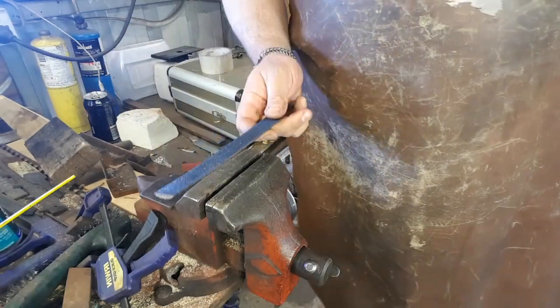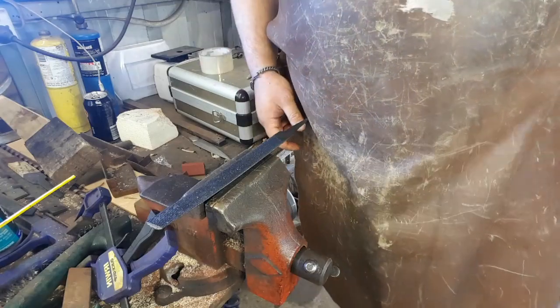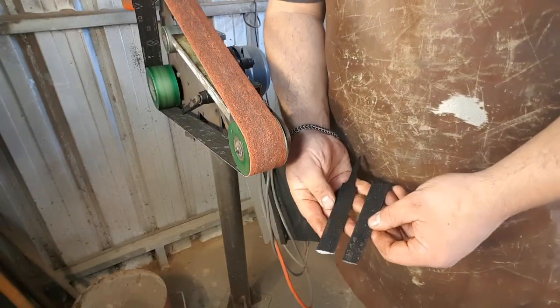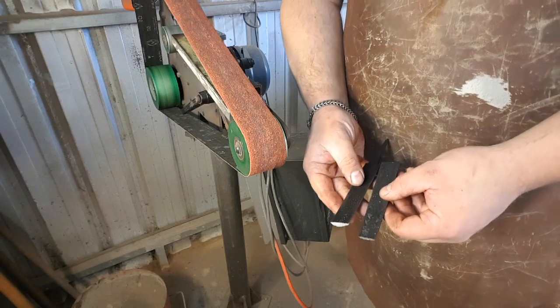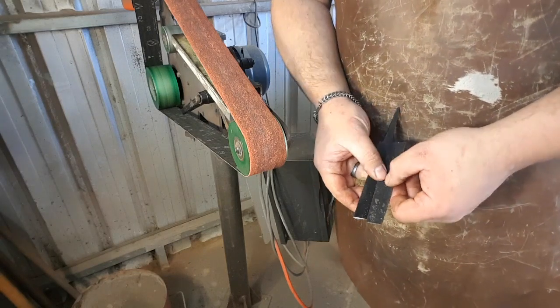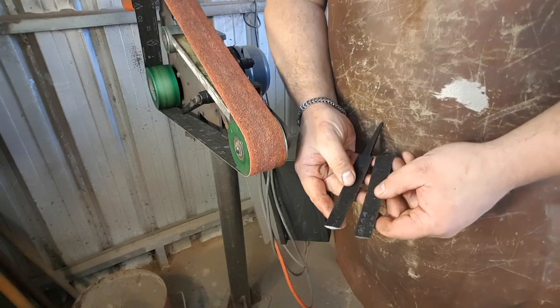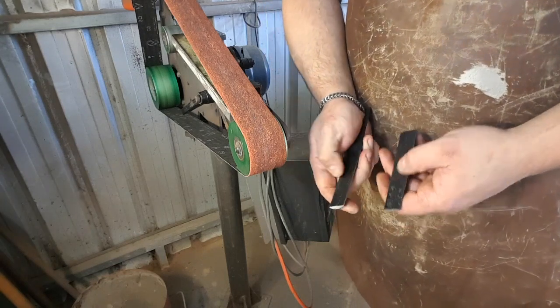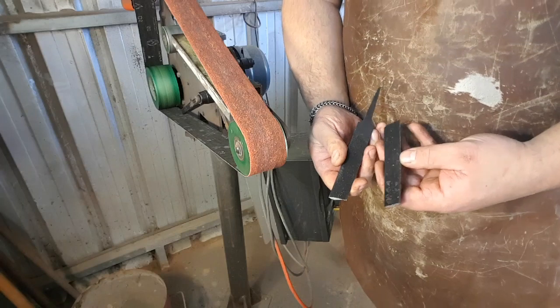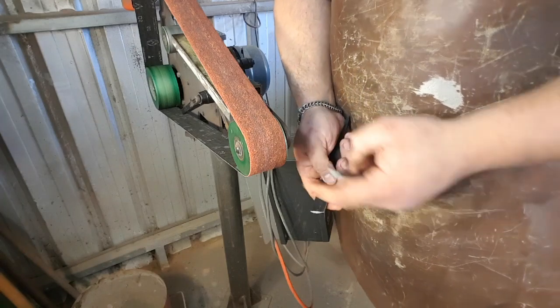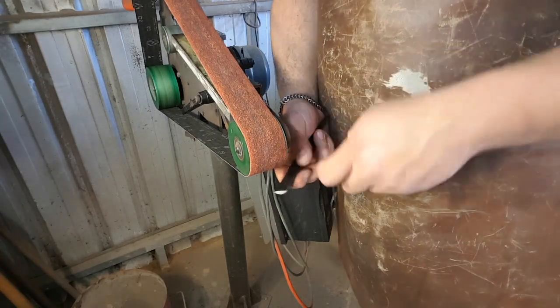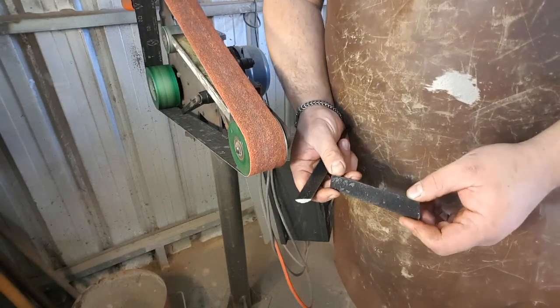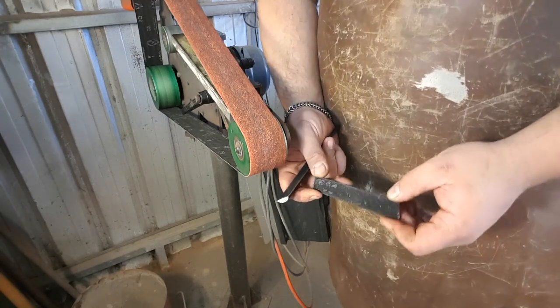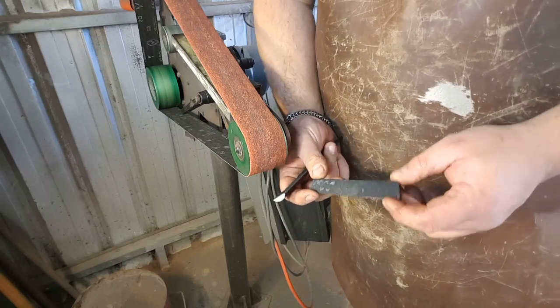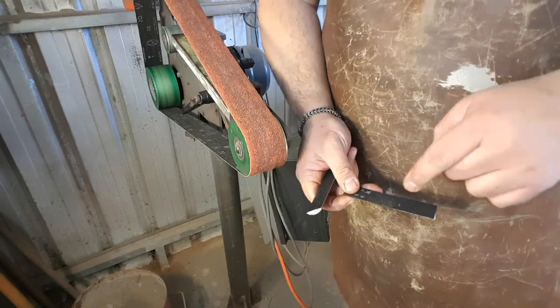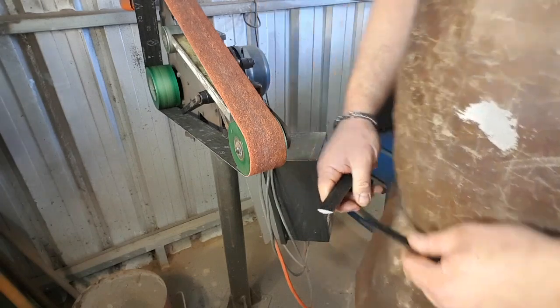So now we need to temper, and there are two methods for that. We'll get into it. Okay, so off camera I just further broke down the file, just one more step. And this is because we're going to use both tempering methods just to show the difference between the two. Now in both methods I want to be able to show the oxidization colors, the heat treating colors, on the surface. What I'm going to do is just take the grinder to it and grind the surface of the steel clean. If you don't have access to an oven, which is one of the methods, then you're going to need to do this anyway because you're going to need to be able to see the colors when you use a torch.